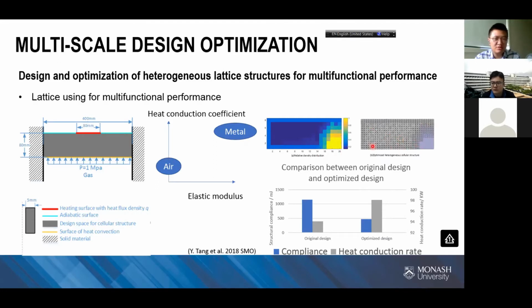For example, here this is an optimal design. We use a computational design approach for the optimization. In this optimal design, you see that we have an almost solid structure here in the middle, and we have this porous structure at the end for heat insulation. But it should be noted that this part also performs another function, structural load bearing. So we also have the pressure here. So in the real design, we should make a compromise between the two functions and find the optimal design which has both better structural performance and better heat insulation performance. So this is the design optimization of heterogeneous lattice structures for multifunctional performance.